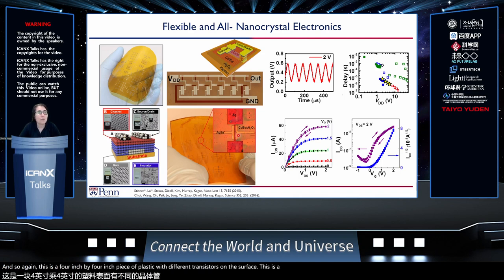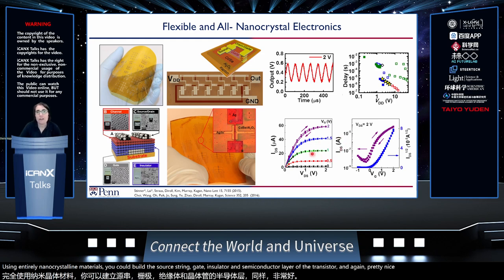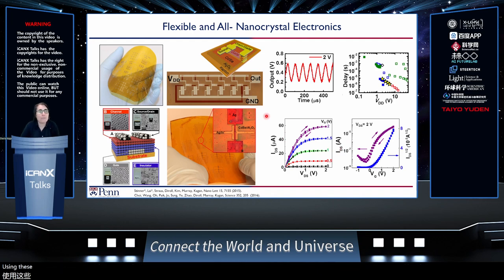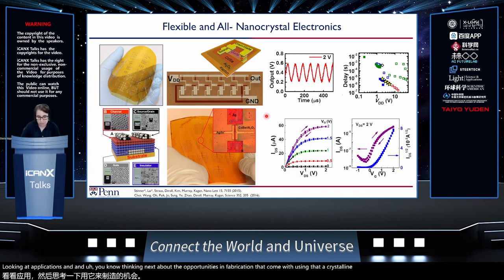This is a highlight of one. We patterned these layers at the time using lithography, but you could see that using entirely nanocrystalline materials, you could build the source, drain, gate insulator and semiconductor layer of the transistor, and again, produce nice looking characteristics using just nanocrystal materials. And so I hope it sets the stage for what's possible in thinking about applications and thinking next about the opportunities in fabrication that come with using nanocrystalline materials.